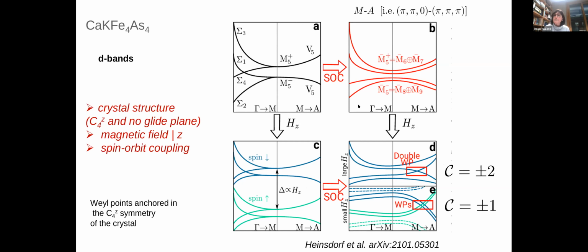So if we combine the two effects, spin-orbit coupling and the application of a magnetic field along Z, at the end of the day, indeed, we are going to have non-degenerate bands. And the symmetry analysis is telling us that there is the possibility of having a crossing along this MA direction, either a crossing where the bands have the same spin polarization but opposite angular momentum polarization, and this will give rise to a double Weyl point, so in fact, a pair of double Weyl points, or, in the case that the magnetic field is not that strong, we can have a crossing between bands of opposite spin polarization, and then we will have a Weyl point of charge plus or minus 1, so a pair of those.